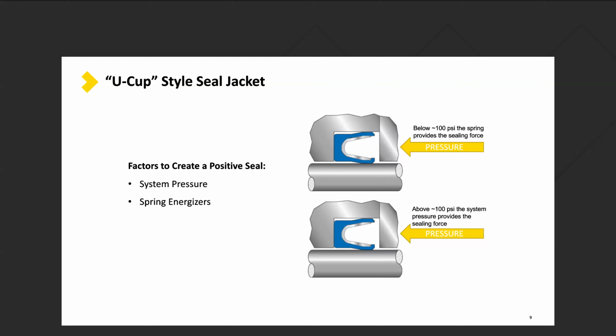So creating a positive seal requires two things: the system pressure and a spring energizer when you're talking about PTFE spring energized seals. Below 100 psi, and again, 100 psi is kind of a rule of thumb, it's not a hard number, but if you're at low pressure, the spring is really creating the sealing force. When you have a startup condition, or a light gas, low pressure situation where you don't have system pressure to actuate the U-cup, you need the spring there to keep things in place. Above 100 psi, that U-cup profile takes over, and the pressure is doing the sealing, where the spring at that point is more or less along for the ride.